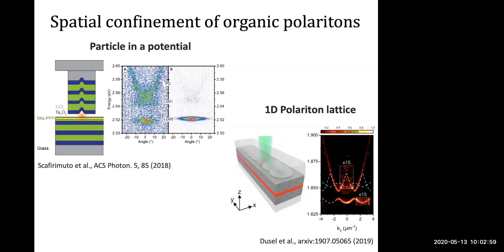So I'll just wrap up with this slide. This is some of the most recent work that has been done on organic polariton condensates. Of course, single confined polariton condensates were realized, but very recently there's been nice work from the group of Sven Höfling, where they pattern one of the mirrors to create a localized polaritonic molecule, if you will, and arrange these in a 1D lattice to create an artificial band structure with a band gap, and then look at condensation at room temperature in one of these lattices. So this is a nice precursor to what is now possible at room temperature with lattices of these polariton condensates.